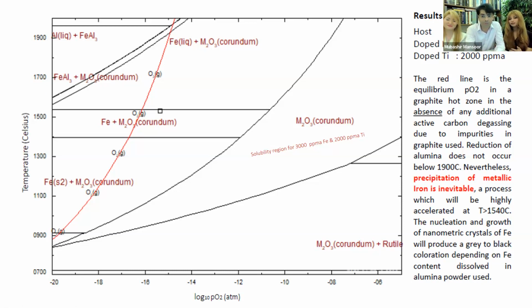So before we proceed, looking at these phase diagrams, we're actually considering this from the dynamic possibilities that could occur. However, we don't know the time frame. Because of the time frame, we have to take a look at the kinetics of the process, as Basha just mentioned. And the kinetics are very interesting because it means if someone waits long enough, they can do complete dissolving of rutile even at 900 Celsius. And 900 Celsius will not leave a great deal of telltale signs.